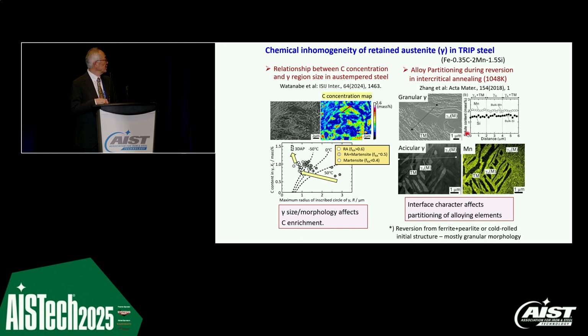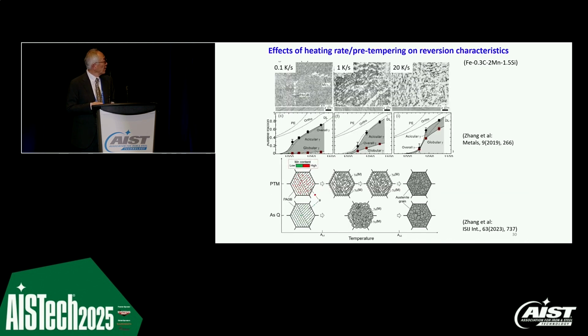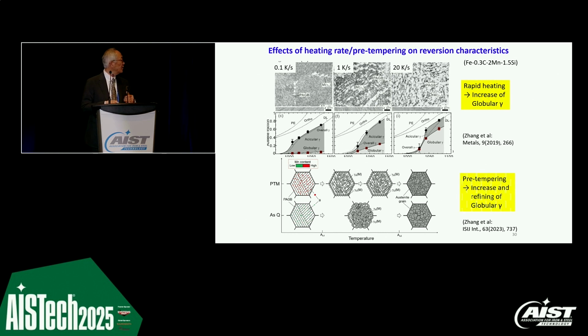For the reversion case, for the granular one, we do not have partitioning of manganese and silicon substitutional alloying elements. However, for the acicular one, when we start from the martensite or bainite initial structure, we can have slow interface migration, and macroscopic manganese and silicon partitioning. That also changes the carbon content eventually. So morphology is very important in the actual chemical composition and phase stability of retained austenite.